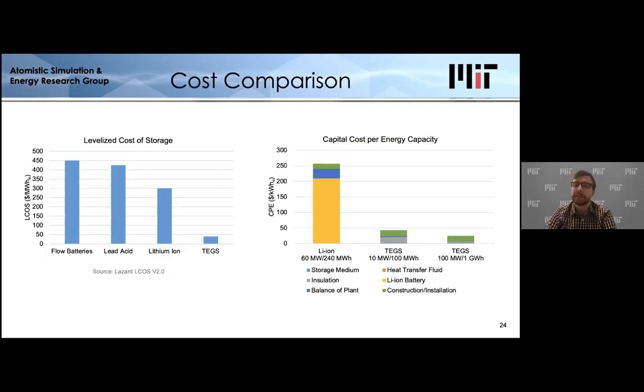So to go into a little more detail on the cost comparison, we considered 2 cost metrics that are typically used for storage technologies. The first is levelized cost of storage, which is effectively the total cost of the system over its lifetime divided by the total amount of energy that the system will store over its lifetime. So if you cycle it more, the denominator goes up and your levelized cost of storage goes down. If you pay less for the system, same thing. Now on levelized cost of storage, our system is very, very competitive on cost. It's significantly below, about an order of magnitude lower than the top 3 battery technologies, which are lithium-ion, lead-acid, and flow batteries.